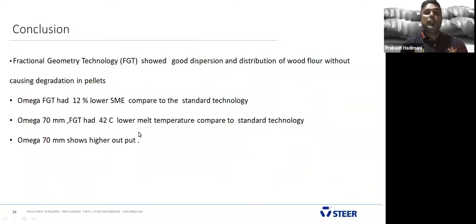Finally, we have concluded for a WPC wood composite. Fractional geometry technology showed good dispersion and distribution of the wood powder without causing any degradation on the pellets. Omega FGT has 12% lower SME compared to the standard technology. Omega 70 millimeter FGT technology had 42-degree lower melt temperature compared to standard technology. And Omega 70 millimeter showed higher throughput compared to the standard technology of 40 millimeter.